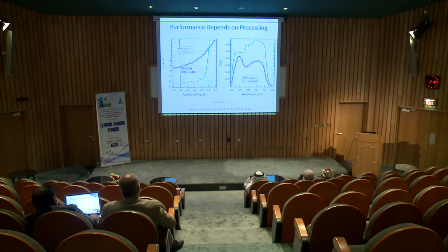And you can see this is the device characteristic of the T1 blending with PC70BM. The device was fabricated in two different methods. One, we use as-cast. It means we make the film, we make the complete device. We call it as-cast. The other case is the green curve, where we add to the solution a very small amount of additive, 0.4% by volume, diiodooctane. This is a high boiling point solvent, and we blend in a very small amount in solution, and you can see it makes a big change in the device characteristic.